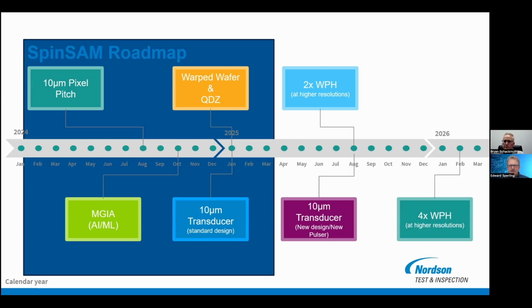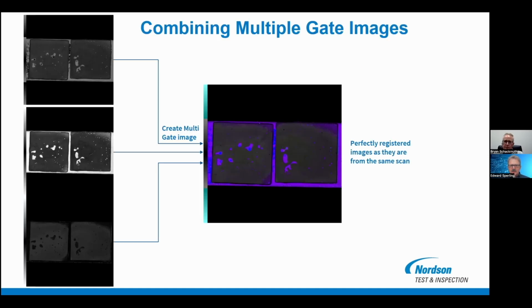Exactly. Where does AI fit into this? Obviously, it's getting a bigger role all the way through manufacturing. Yeah, exactly. In the system we're looking at, we're generating images. And traditionally, we've used a threshold to analyze those images. So if a pixel is bright, above a certain threshold, it's a defect. With the complex structures of today's parts, that simple threshold type analysis is no longer possible to capture the defects.